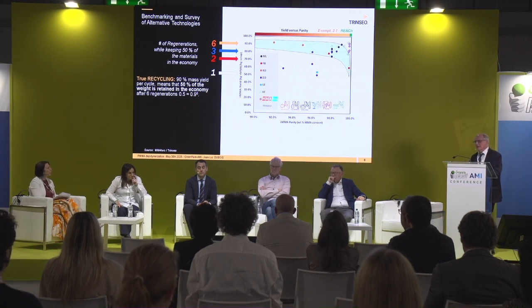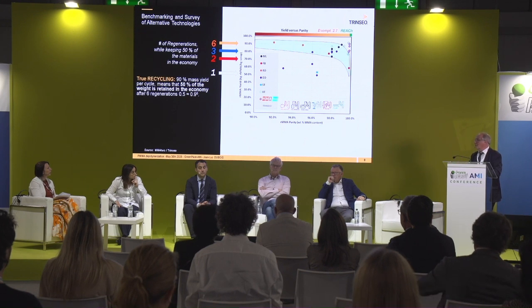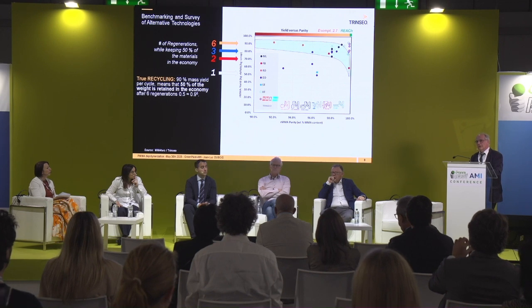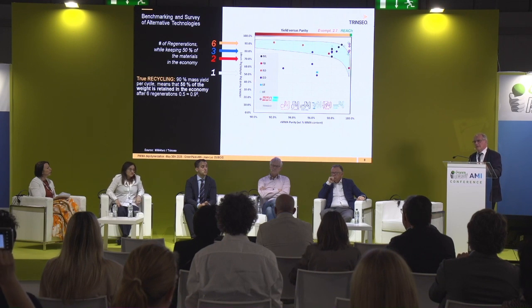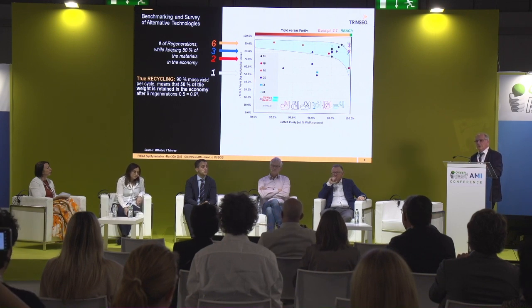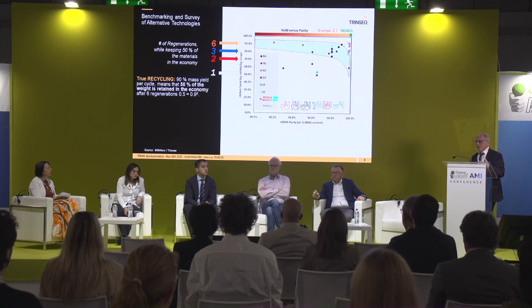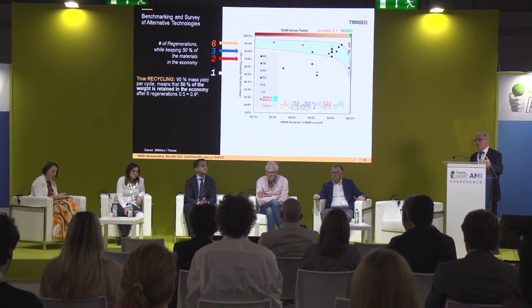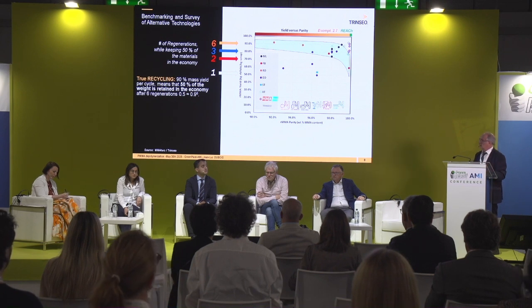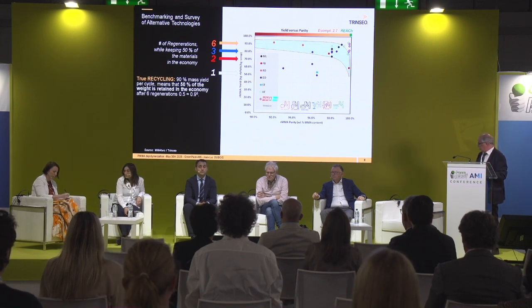What I want to stress in this case is when you have a technology which is able to achieve 90% yield, and whatever the purity, but the higher the purity it is, 90% yield, it means that you can recycle 6 times your polymer and still keep 50% of the carbon in the economy. And this should be our driver for sustainable technology and sustainable materials, is to keep as long as possible the carbon in the economy.